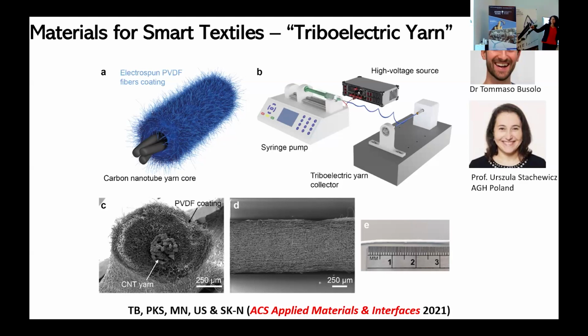And he then basically electrospun PVDF. You can kind of see what it looks like in cross section. So that's our electrode essentially, and this is the PVDF. And it's great because you have a lot of surface area, because these are fibers, which is also what you want for a triboelectric device. The more the surface area, the higher the surface charge. And these are the kind of fibers.